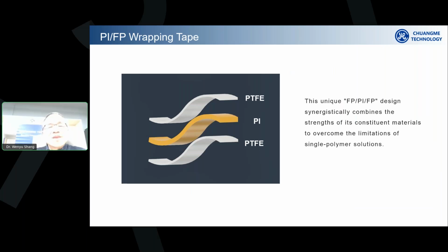previous two slides, right? And here is a picture, and you can see the PI sits in the middle, and we coat a specially modified PTFE coating on both sides of the polyimide film. So this PI would offer the very high temperature resistance as a core performance, and these two PTFE sandwiching structural layers would offer protection to the PI film, and would melt and form a continuous insulation layer in the final cable production procedure.